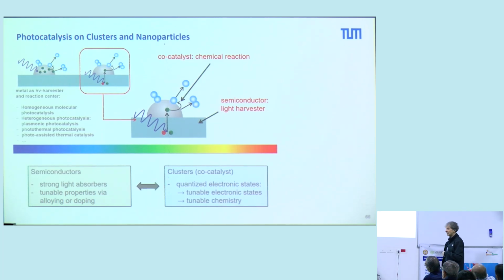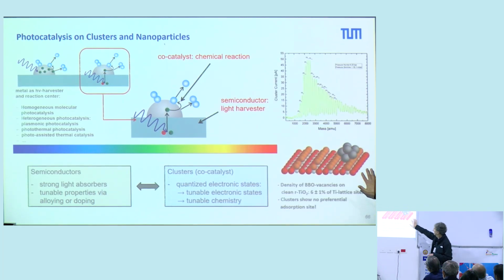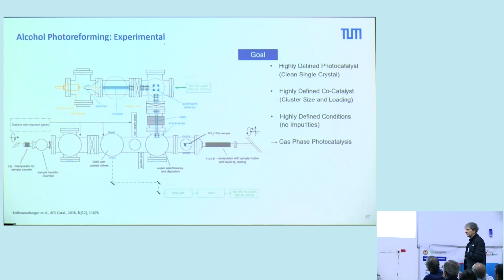On the co-catalysts, we are in the non-scalable size regime. We have quantized electronic structure, and so we expect different behavior on these species. Our samples consist of a titanium oxide surface, and then we have these size-selected clusters on this surface. Also important is that on this titanium oxide, we have so-called BBO sites. These are bridge-bonded oxygen vacancies. That means you have an oxygen vacancy. We'll see that this will be relevant. And so we are trying to study these photocatalytic reactions on these systems.